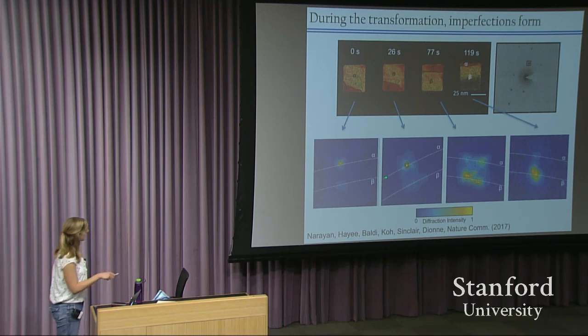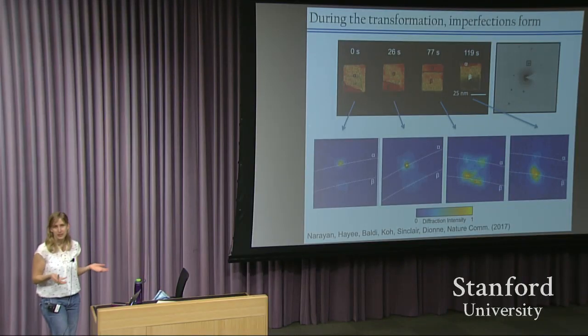So the innermost circle corresponds to beta, so basically has a smaller radius corresponding to a larger lattice constant. And then the outermost circle corresponds to the alpha phase. So right at the beginning of the transformation, we have coexistence of alpha and beta. But in this diffraction pattern, you'll notice that the spots are very circular, corresponding to essentially a very good crystal. There aren't many defects or imperfections in this crystal.